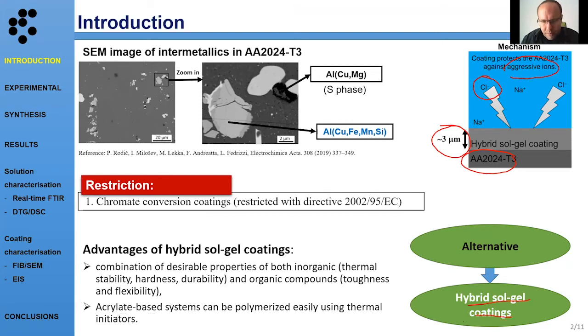The reason is that this approach has many advantages, and one of them is definitely that we can combine both inorganic and organic compounds in one material. That means that we can tailor and choose different compositions, and so get a material with different thermal stability, hardness, durability, and so on. Moreover, these hybrid sol gel coatings can also be modified with acrylate-based systems. That means that these kinds of molecules can be easily copolymerized in our hybrid sol gel network.